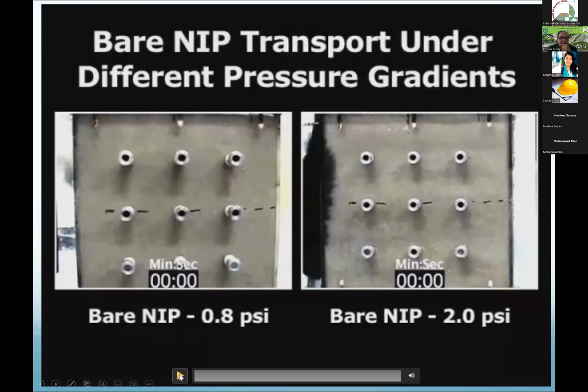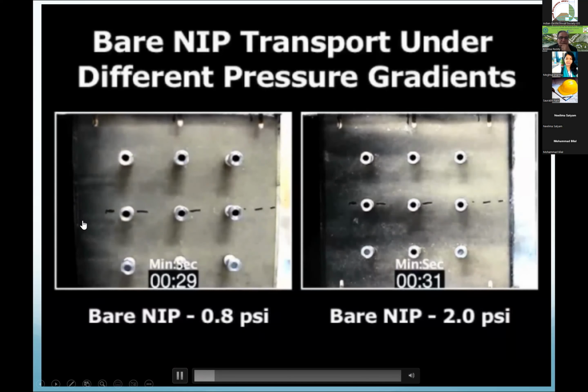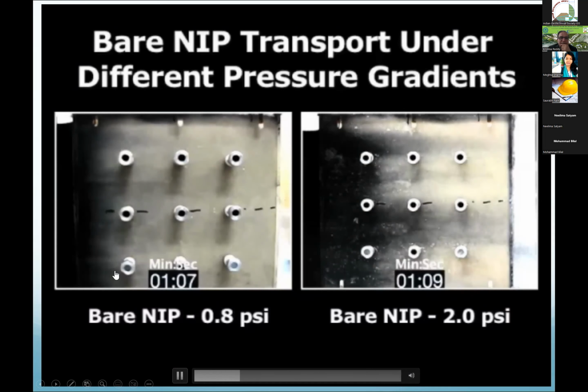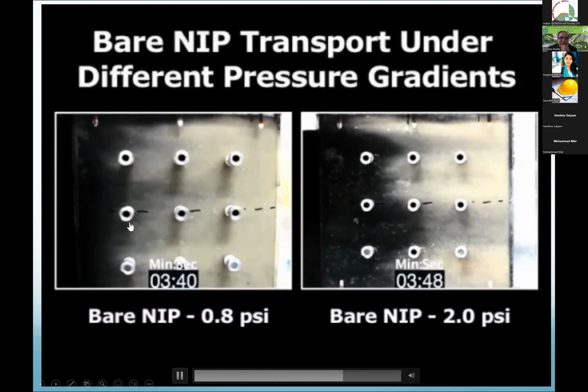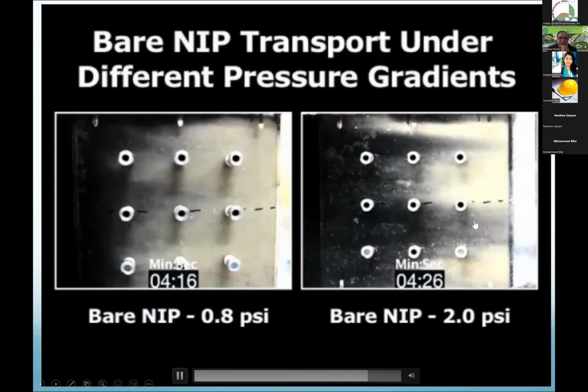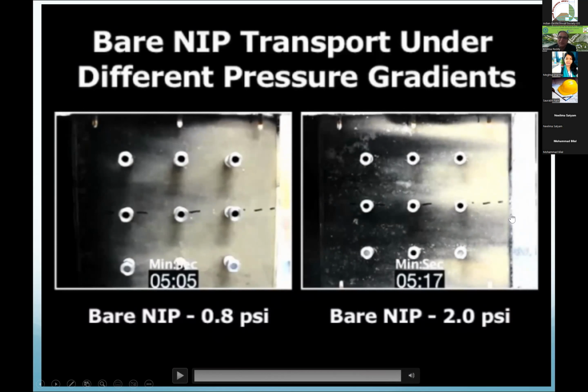So let's see if this video works. If it works, then it's good. See this one, we injected from the bottom here, from one end, and the black color is the iron. So it is 0.8 psi. It's just spreading only this area. At 2 psi pressure, you see this one is spreading a larger distance, but it's all heterogeneous. See, it's not uniform. You flush it more, you see that one coming out, but it's non-uniform. When we want to flush in a real world application, it has to be completely uniform, right? So this is the bare nip. If you don't put anything, at low pressure you get very little transport. Nothing comes out here. Nothing gets transported. But if you have high pressure, then you will have this random distribution that goes on.